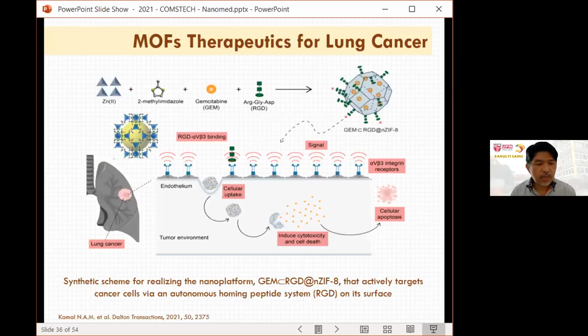So I would like to share with you our latest work, which was just published in Dalton Transactions, where we establish a versatile nanoparticle through a straightforward method. We change the common method, which is actually high temperature. So in situ, including the gemcitabine, and in this case, we conjugated with the RGD. The RGD is actually the autonomous homing system of this peptide, arginine, glycine, and aspartic acid, via a one-pot solvothermal reaction. So in this work, we can show that the RGD peptide is a binding ligand that homes to the integrin receptor alpha v beta 3, which is overexpressed on tumoral endothelia.